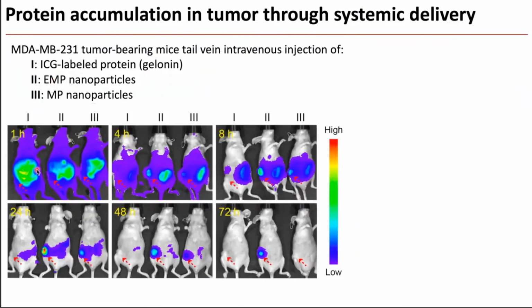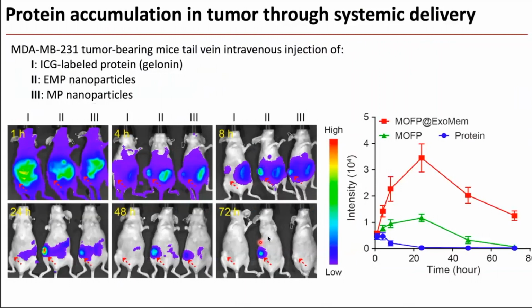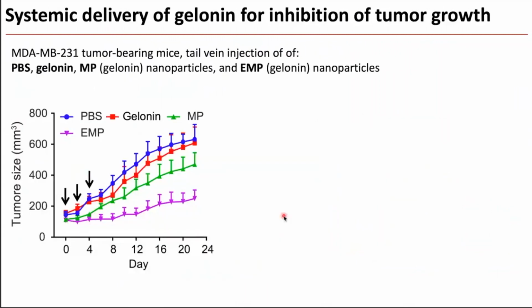We monitored the mouse from 1 hour to up to 72 hours. As you can see, we see significant accumulation of these particles even after 72 hours for the case of nanoparticles enclosed with EV membrane. And then this is the quantification of the data.